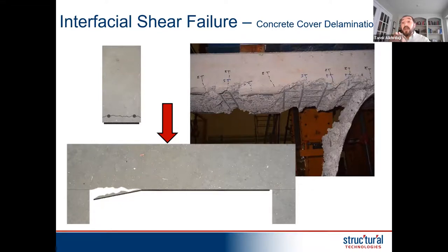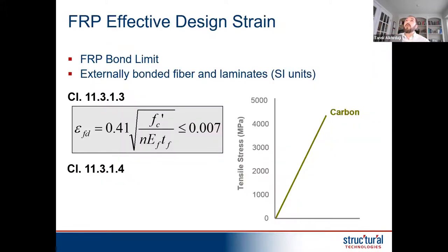The epoxy is actually stronger than the concrete. The epoxy has higher tension and higher compressive strength. It's the concrete itself that at some point will give in and basically shear off at the weak link, in this case, at the rebar cage. So the standards give me the design criteria that tell me the maximum strain I can achieve in the FRP to prevent that failure mode. So it's not something we don't know, we know and we design for it.